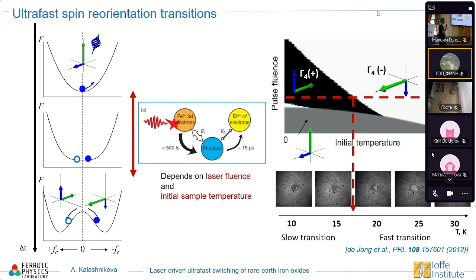It's kind of a phase diagram. So here at low fluence and low initial temperatures, nothing happens. And at high fluences or high temperatures, we have transition to this or to this state. We can verify it experimentally. So this is the final state. After the excitation at low temperatures, we have a black domain. And after excitation at higher temperatures, we have a white domain. Also, we had the very same pump polarization.